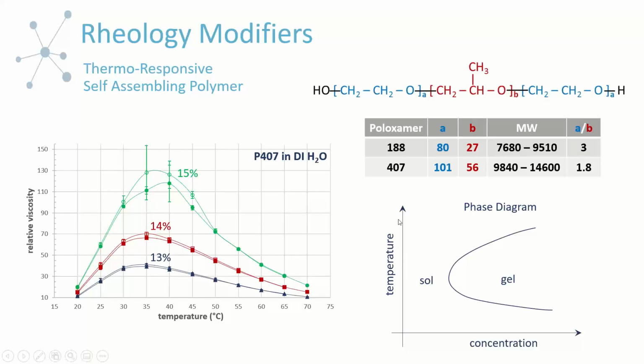So for these types of materials, there's actually a phase diagram. So if we look at the temperature as a function of concentration, you can actually develop this for your particular poloxamer, which can vary in terms of overall molecular weight and the ratio of the blocks. So what you can do then is find out, for a given concentration, what temperatures are you in a viscoelastic solid gel type state and what temperatures are you in a fluid state. And the viscosity measurement can sort of guide you in developing this phase diagram.